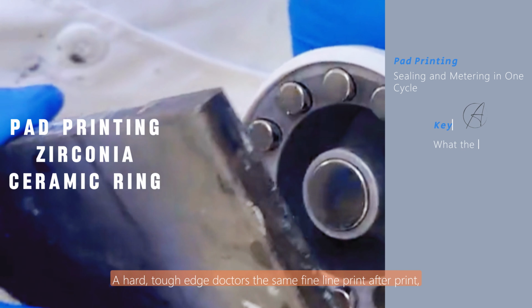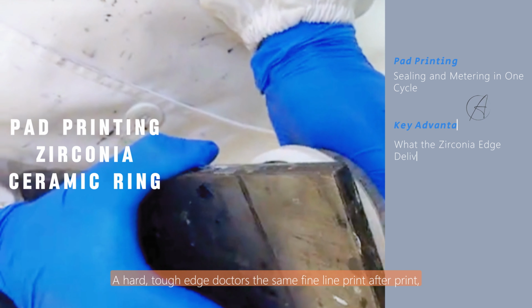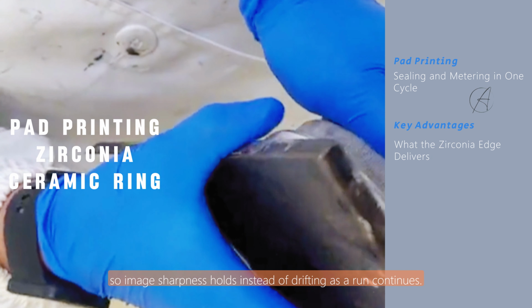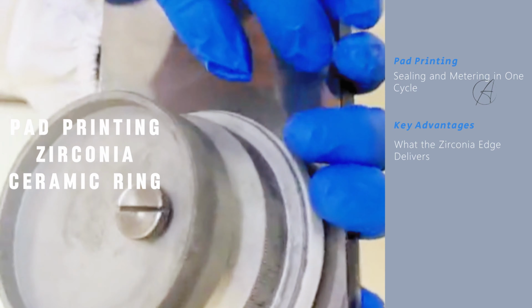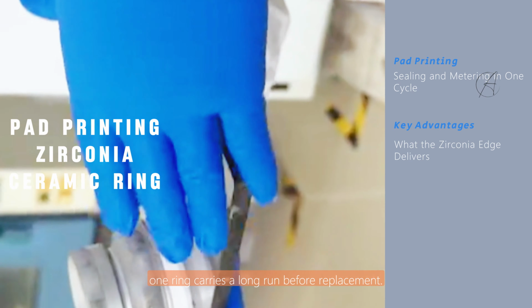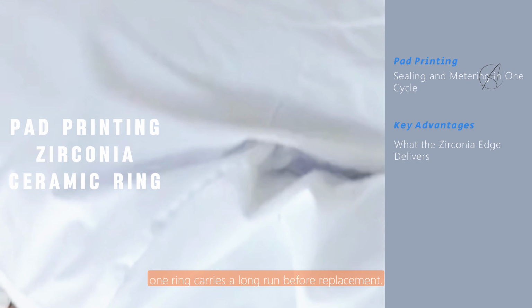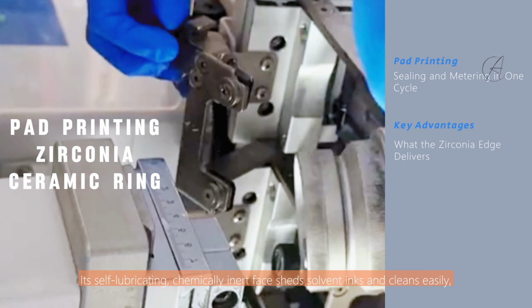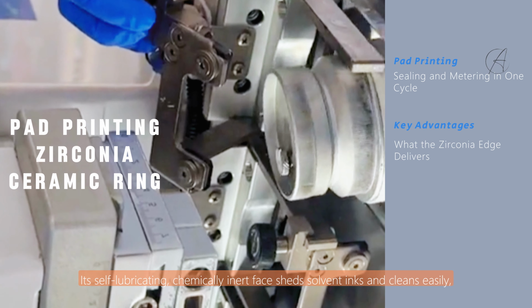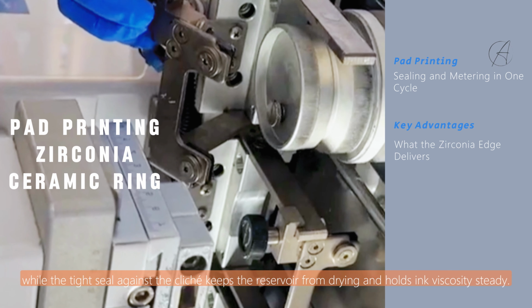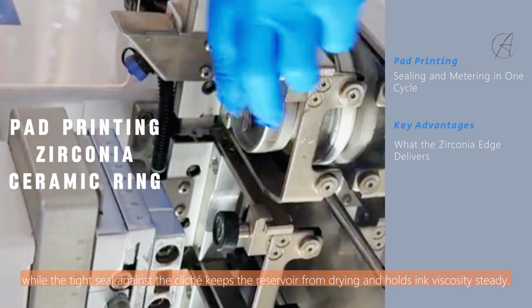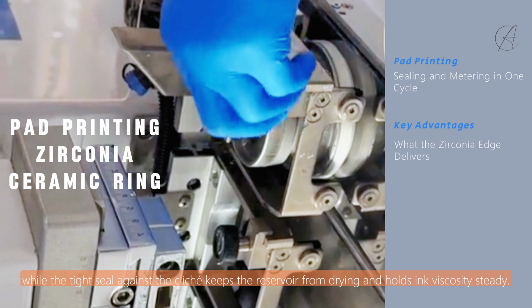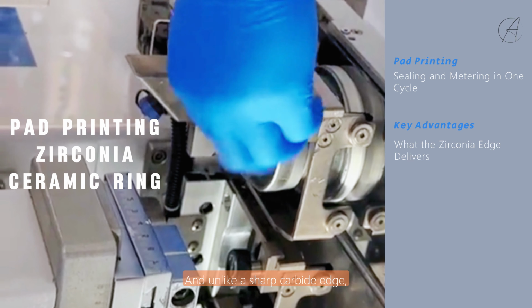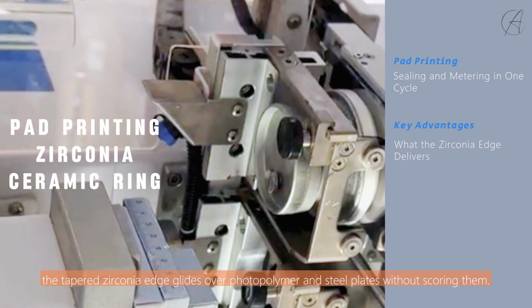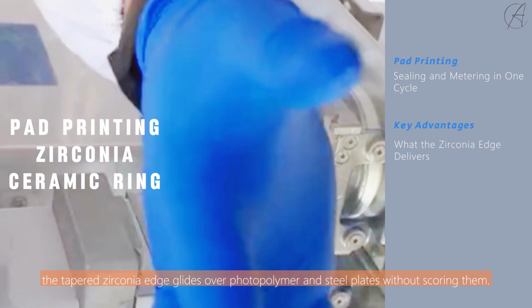A hard, tough edge doctors the same fine line print after print, so image sharpness holds instead of drifting as a run continues. Because the edge wears slowly, one ring carries a long run before replacement. Its self-lubricating, chemically inert face sheds solvent inks and cleans easily, while the tight seal against the cliché keeps the reservoir from drying and holds ink viscosity steady. And unlike a sharp carbide edge, the tapered zirconia edge glides over photopolymer and steel plates without scoring them.